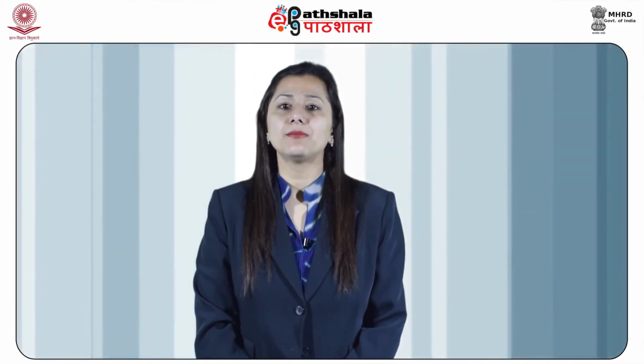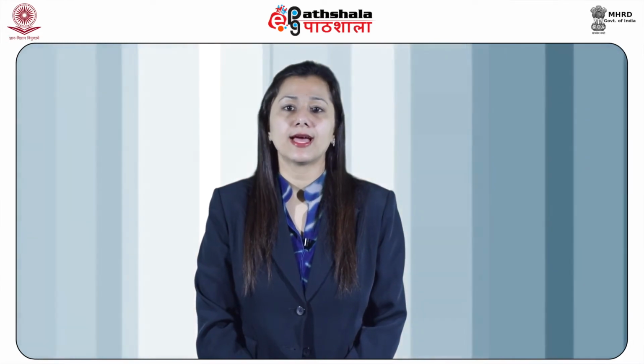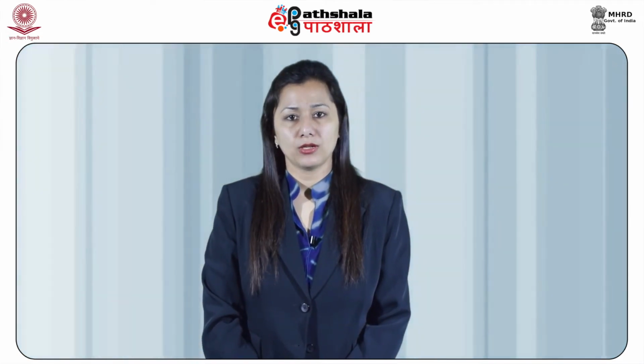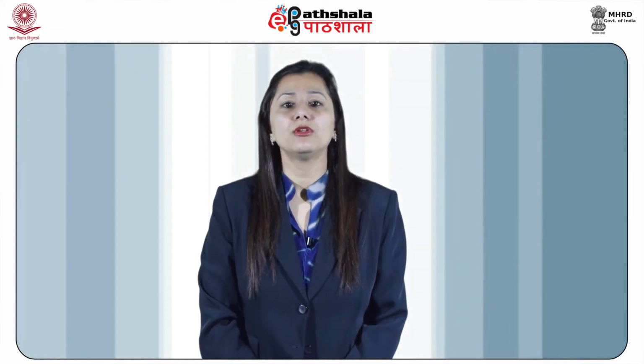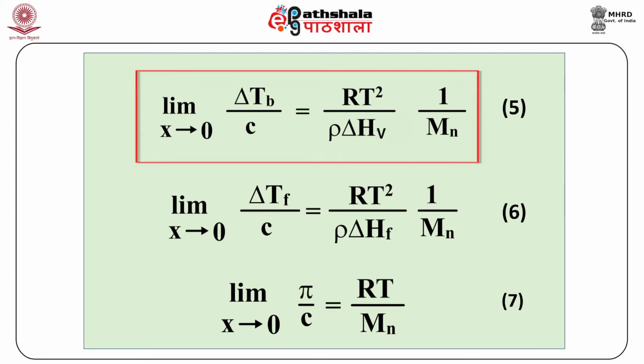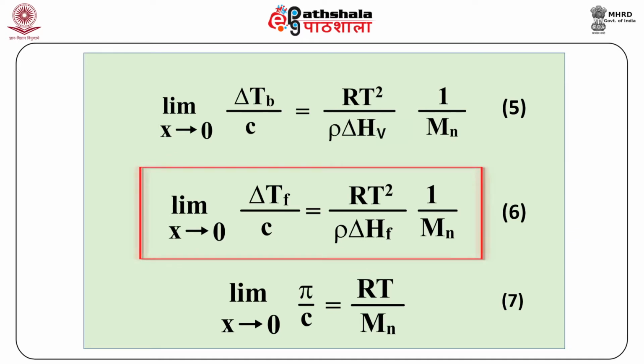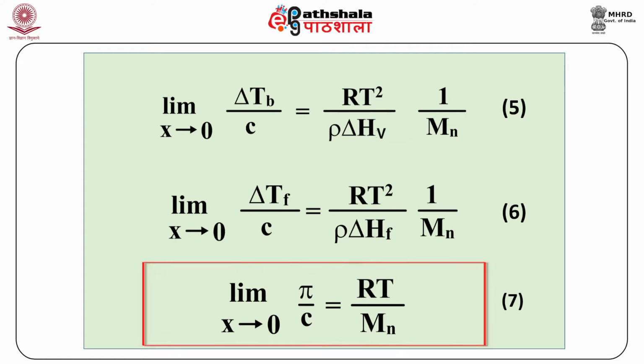These methods require calibration with low molar mass standards as they may produce reliable results for polymers with molar masses less than 30,000. The working equations for ebullimetric, cryoscopic and osmometric measurements are as follows. Delta Tb by C, limit C tending to 0, is equal to RT squared by rho delta HV into 1 by Mn, as equation 5. Delta Tf by C, C tending to 0, equals RT squared by rho delta HF into 1 by Mn, as equation 6, and pi by C, limit of C tending to 0, equals RT by Mn, as equation 7,